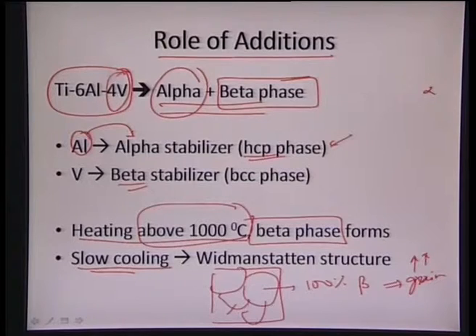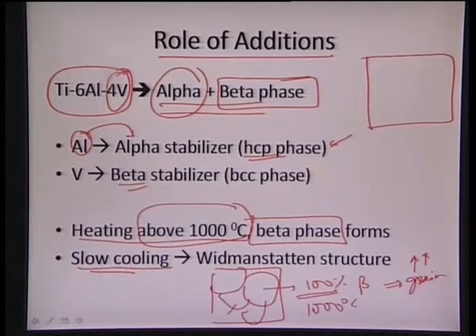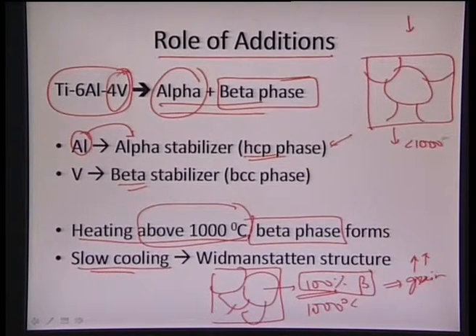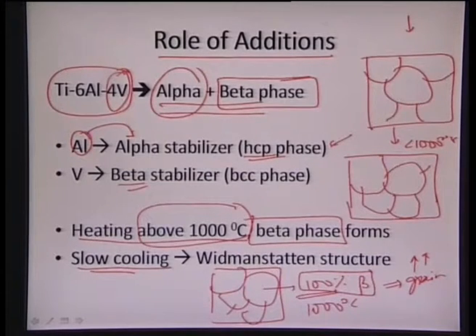I'll just draw it here, that we see a structure in which initially we will have only beta grains once it is heated at higher temperature. So in this case we have greater than 1000 degrees centigrade, we see completely 100% beta, and as soon as we start cooling it down slowly, we will see the increase in the grain size. So we will observe increased grain size, and after certain temperature below 1000 degrees centigrade, we will see the nucleation of alpha phase as well. So in this particular case, we will see bigger beta grains which were stable at more than 1000 degrees centigrade, and we see nucleation of alpha phase. So in this particular case, we had these larger beta grains, and in that we see a needle like secondary alpha phase. And this structure is not that good.